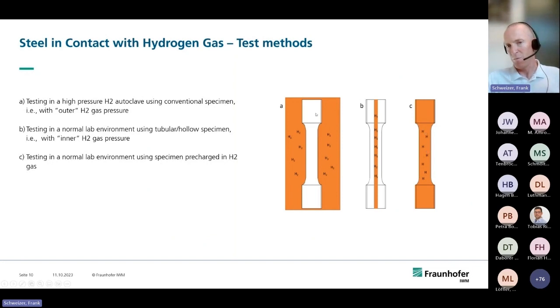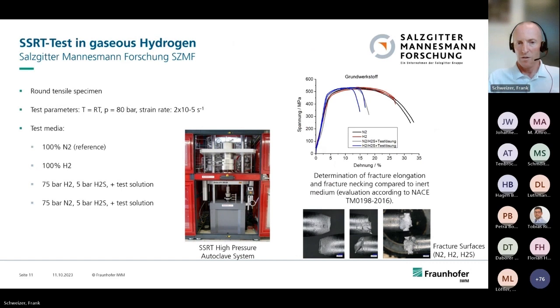You can put them in an autoclave system and put hydrogen around this, and you can make a hole on the inner side of the samples and test the hydrogen or the hydrogen mechanical interaction from the inside of the samples. So one case is you see here a slow strain rate tensile test. This is a quite big one in our house.